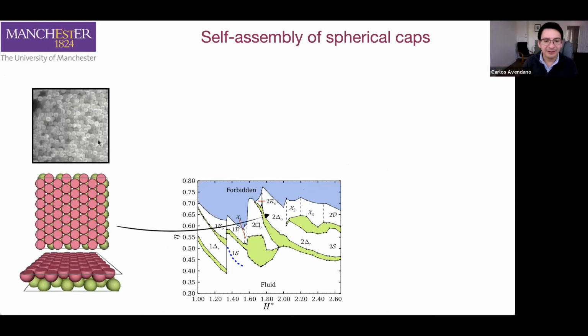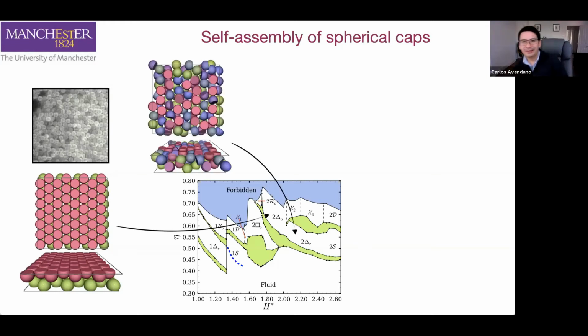But now things will become very interesting. If we increase the separation between the two plates a little bit more, and we give again enough space to the particles to rotate, they will do it. And they will do it in a very interesting way. If you look at the center of mass of these particles, you will see that the particles are actually located in a hexagonal lattice, the same hexagonal lattice that we have here. So you can see quite clearly the formation of these stripes.